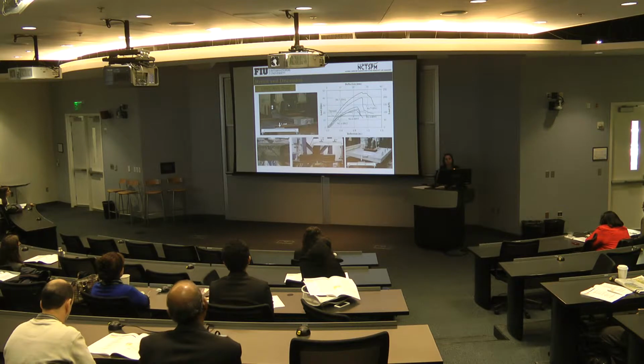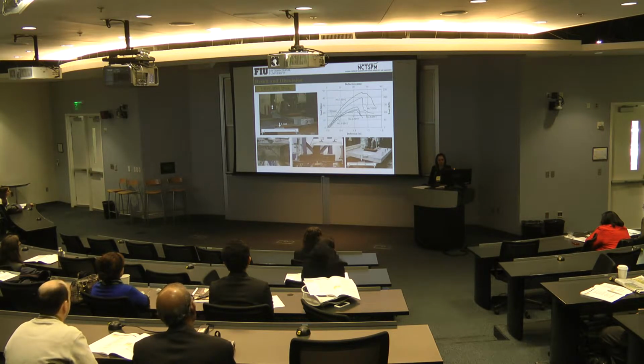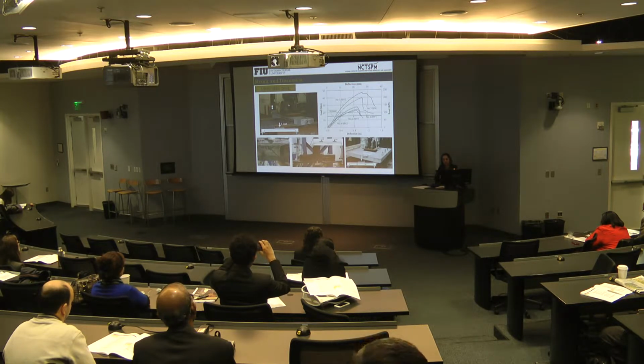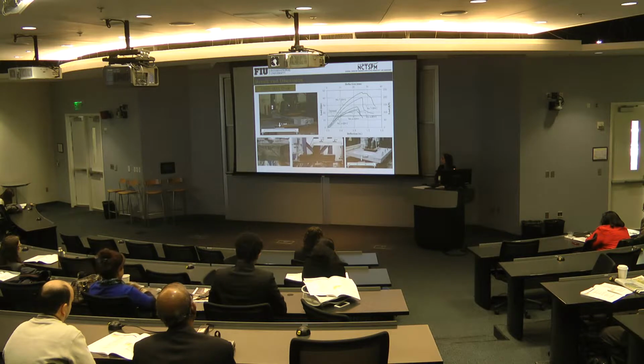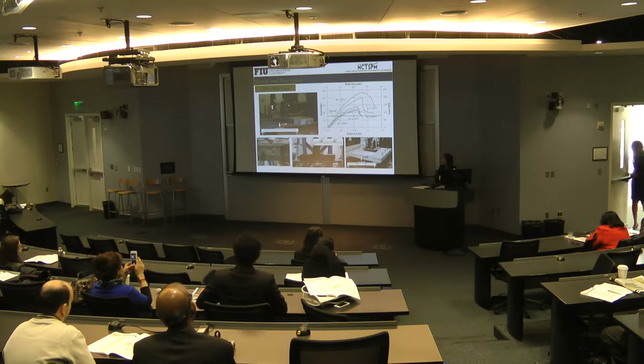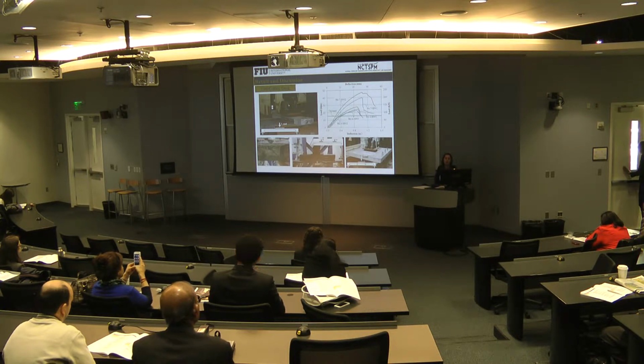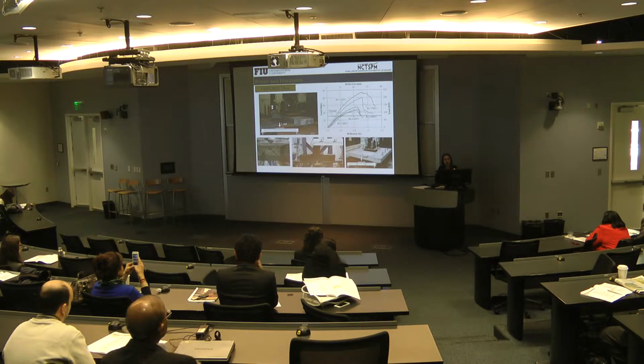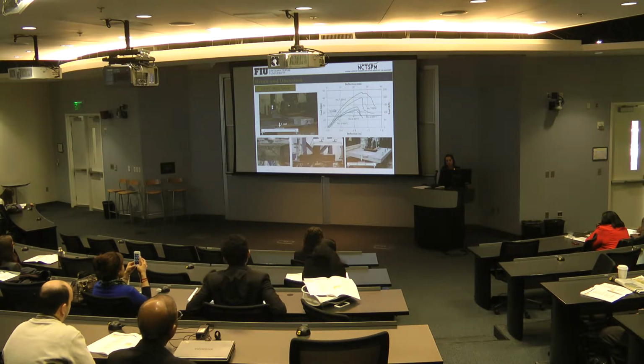The second section that we used was the UHPC waffle deck. For the first set of tests, the overall section height was 5 inches, and the number of bars that we used was 7. So as can be seen in the graph, for the first 2 sets of tests, we came up with an ultimate load of about 45 something, which is much higher than the proposed demand. So we reduced the section to as low as 4 inches of height, and the longitudinal rebars became 5, number 5. And as can be seen, the result shows that it's still a little above the demand, but we cannot go further because there are some limitations for the height.